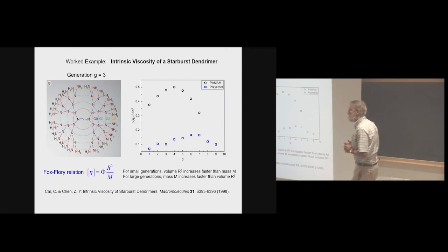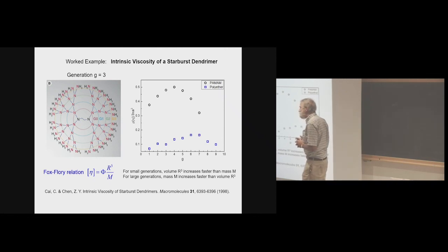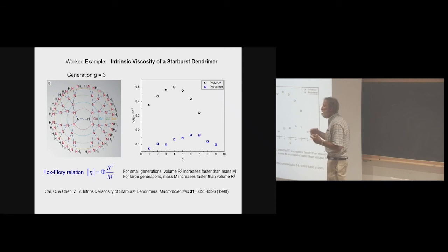Yes? How should we think about the friction in a melt, like the dissipation in a melt, when there is no solvent? Well, that's a great question. So we can't relate it to solvent viscosity. There's no solvent, right? But there's always still some frictional resistance, because that friction coefficient is essentially the monomer time, the time scale for individual monomer motion in different units, right? So there's always some time scale. I think the tau zero maybe has, for me, a little more physical meaning than friction in this case, right? But yeah, the two are the same thing. It's just they have different units.